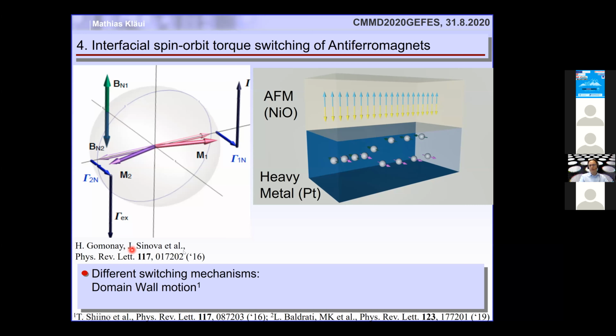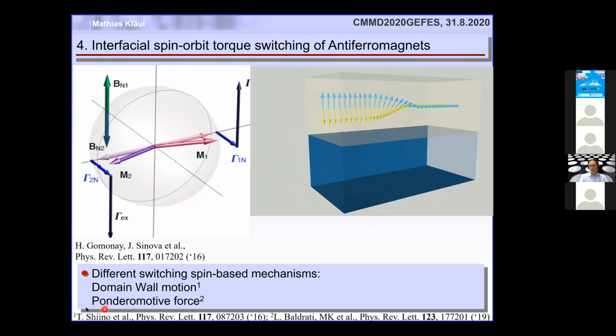However, the problem is that the direction of the domain wall motion depends on the chirality. And if there's nothing that breaks the chirality, there will be a change in the spin structure. There will be no net switching. And for that, Helen developed a different approach, the ponderomotive force, where you actually have a 90-degree change of the sublattice orientations of the Néel vector, and she's going to talk about this in more detail.